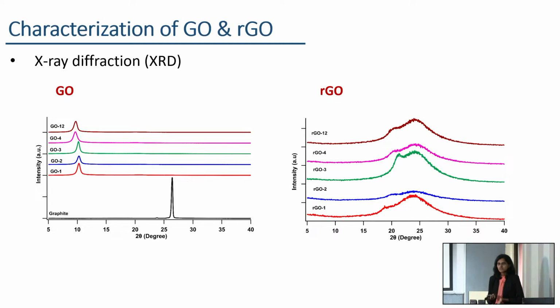Then after the reduction, the XRD spectra of these RGO samples show a broader and low intensity diffraction peak in the range of 17 to 30 degrees. This broader diffraction peak shows the amorphous structure of these reduced graphene oxide after the reduction process. That is due to the removal of basal plane oxygen functionalities during the thermal reduction process.